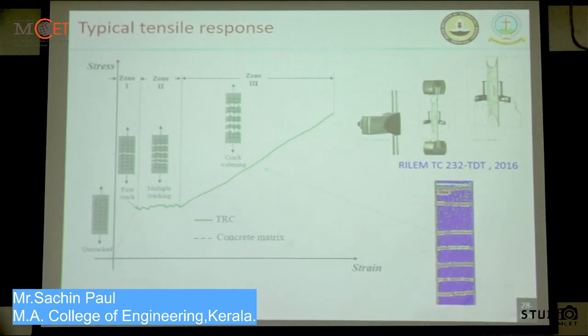There's leakage. But it doesn't matter whether you have a crack. What matters is whether the crack width is big enough to produce seepage. Since you have distributed reinforcement, the biggest advantage of TRC and its predecessor ferrocement is that you have a lot of distributed crack formation. With conventional reinforcement you would have, say, X cracks. Instead of X, you have 20 cracks. So the entire crack width is distributed along these 20 cracks, and that produces very, very small crack openings through which no seepage happens in the system. So distribution of cracks is one of the biggest advantages of TRC. Thereby, we reduce the crack width at a particular location. You are distributing it in a system.